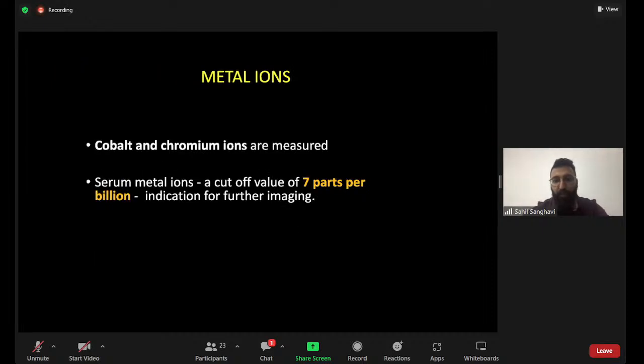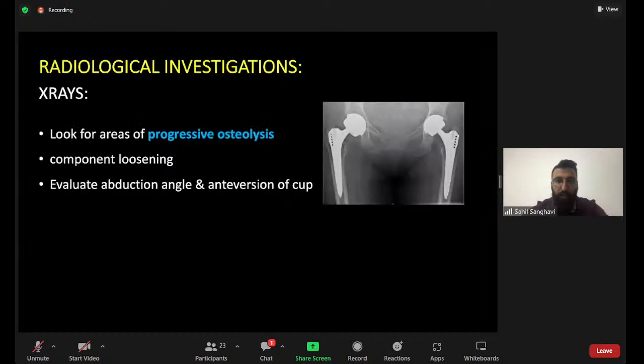Metal ions, you must perform blood tests to detect the serum levels of cobalt and chromium. So usually the cutoff value that indicates metal sensitivity or metallosis is 7 parts per billion. And this is an indication for further imaging of these patients.